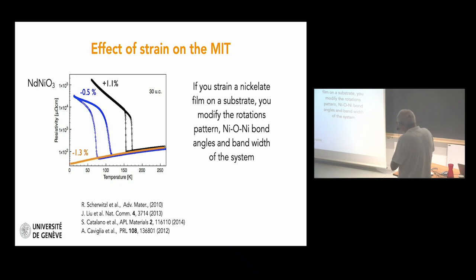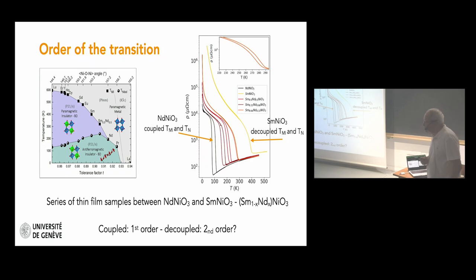This is what you see here for neodymium nickelate, resistivity versus temperature, films grown on different substrates, and you see that although the change in rotation pattern is quite complex, you can modify dramatically the metal to insulator transition from about 150 K to maybe 100, and eventually the films stay metallic all the way down to low temperature. Let me say something about the order of the transition. Andrea mentioned yesterday that neodymium nickelate has a first order metal to insulator transition. This is what you see here. Again, resistivity versus temperature. This is neodymium nickelate, and you see this nice hysteresis that you already saw yesterday.